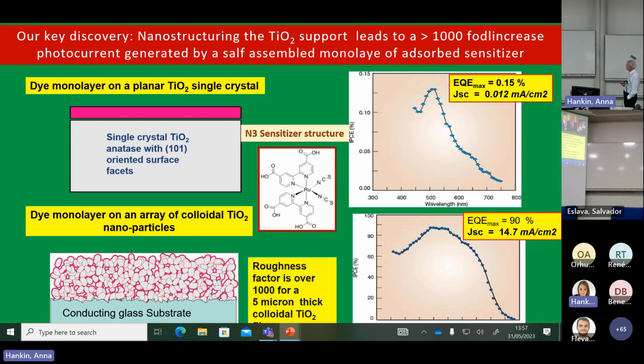I should tell you that the colloidal particles have mainly 101 surface facets. So we made a single crystal anatase TiO2 with a 101 facet exposed and sensitized it. And you can see here the current, 0.012 milliamps, so that's 12 microamps per square centimeter. Better than what people got before, but not impressive. Instead, when you now use this mesoscopic colloidal layer, we get 14 milliamps, so you have a factor of 1,000 more current out. And that was an amazing phenomenon that is quite hard to understand.